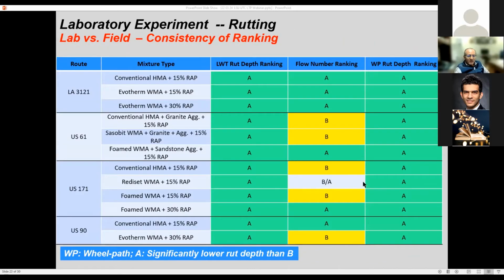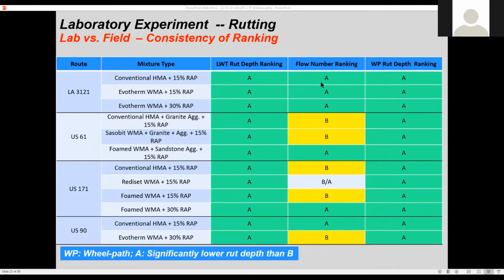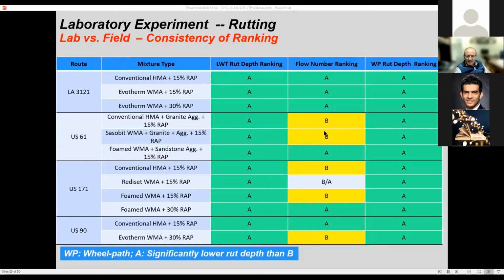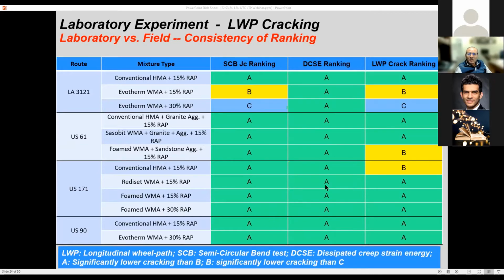The second objective was, well, how did these laboratory tests compare to these measurements? So these are the 4 sites. This is each section in each site. You would see that this is the high temperature laboratory test, another high temperature laboratory test, which is LWT, and flow number. And the last column is the field measurement. That kind of gives you a snapshot of whether they have a similar ranking or a different ranking. And you could see that in these cases, some of them have a slightly different ranking than the one measured in the field.